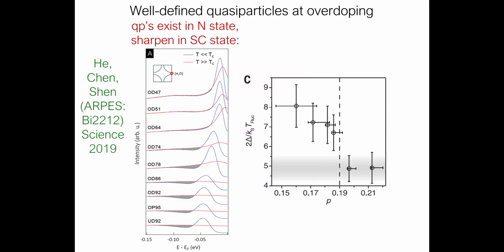There's been a lot of work on this, so let me just show you a couple of things about how quasiparticles, seen by ARPES, I think this is from ZX Shen's group and Yu He, in Bi-2212, sharpen up as you overdope. Even in the normal state, you see well-defined quasiparticles. And at the same time, the gap that you measured from the pullback of the EDC decreases as a function of doping, and the gap ratio becomes closer to what you might think would be a BCS weak coupling value, like 4 or 5 for 2Δ over k_B T_c.